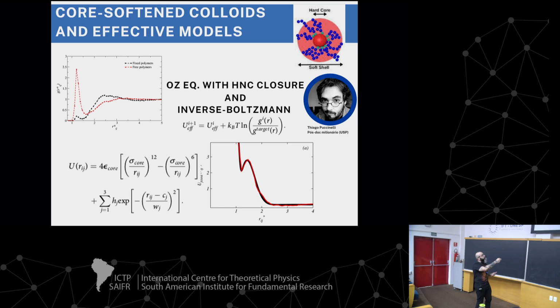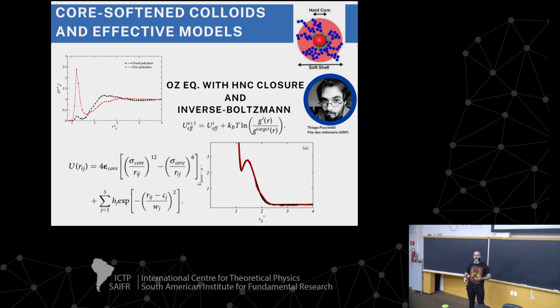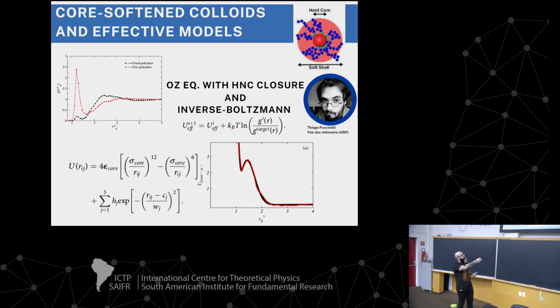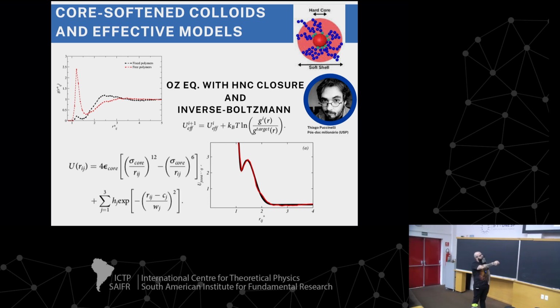From the g(r), we use the Ornstein-Zernike equation with the hypernetted chain closure, and also the inverse Boltzmann procedure, where basically we say we want to get this g(r), so we try to guess a lot of g_i(r)'s to reach our target g. With this, we can get the effective potential. We use the idea of a Lennard-Jones plus a lot of Gaussians. Why we use this idea, we will see in the next two or three slides. But here in red you have the exact result from the inverse Boltzmann procedure, and in black the approximation using this potential and some parameters.